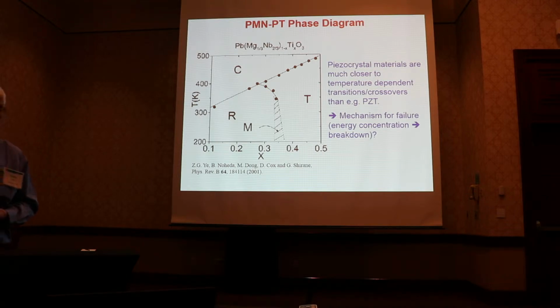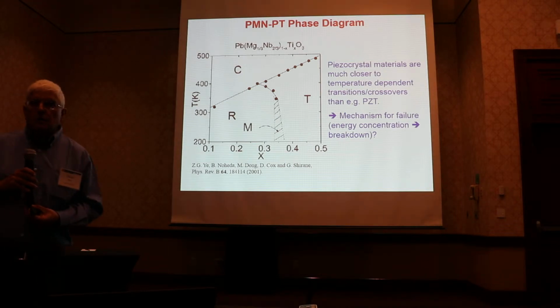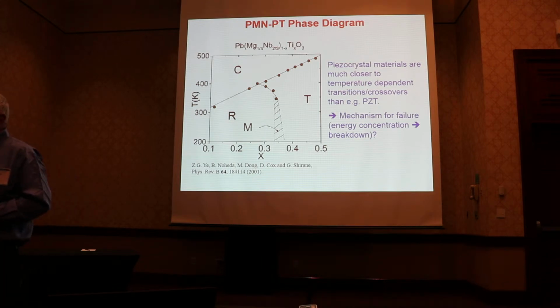So the idea was you could have a thermal runaway effect, where when you drive the transducer, if there's a local place where the energy is concentrated, then the temperature will rise, then the dielectric response will rise, and that will concentrate the energy there. And then, of course, it becomes a balance between the rate at which you put energy in and the dissipation of energy through thermal conductivity. And so it becomes a question of thermal conductivity.